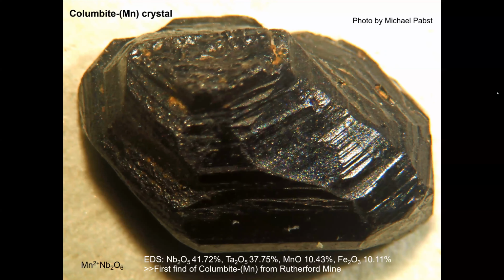On this one, I will readily admit to cheating a little bit, because you can't really tell because of the logo here on the lower right. But in this specimen, there was a slightly larger presence of manganese over iron in the sample, which identifies it just barely, those are Tony Nickisher's words, as an example of mangano-columbite, or columbite-Mn, which would be the third species discussed so far that is not listed in MINDAT.